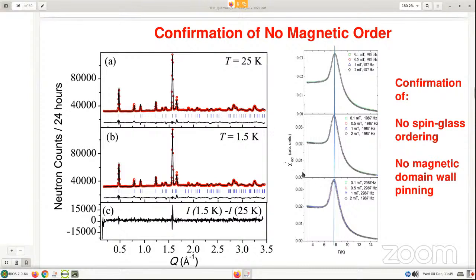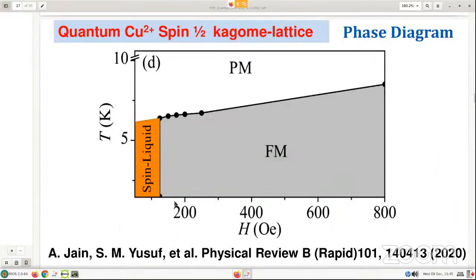In fact, AC susceptibility plots are shown here as a function of temperature at different applied DC fields and different varying frequencies. From this, we do not see any shift, and it confirms that there is no spin glass ordering. There is no magnetic domain wall pinning. Otherwise, we should have seen the shifted behavior. So that means this transition is nothing but the transition from this high temperature paramagnetic to a spin liquid kind of phase.